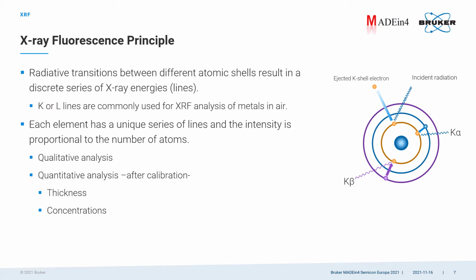Each element has a unique series of fluorescence lines, which allows for qualitative analysis of the sample. The measured intensity is proportional to the number of atoms in the irradiated sample volume. So if we have a reference with a known quantity of the element, we can calibrate the system and perform quantitative analysis. We can measure the thickness of metal films and stacks, or measure the concentration in alloys. It's a beautiful technique because it is non-destructive and requires, which is especially the case for semiconductor wafers, no sample preparation.